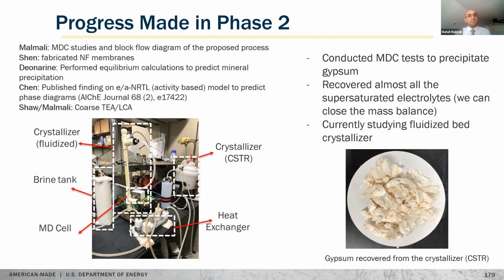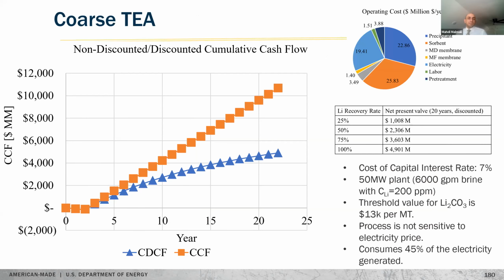So with Deonarine, we did some very basic thermodynamic studies on equilibrium calculations to predict the mineral precipitation. And also Chen published a very accurate activity-based model called e/a-NRTL to predict the phase diagrams for lithium chloride. And in the next phase, we want to do experiments with lithium carbonate and lithium hydroxide in order to get this model also working for them, and essentially use the model from the beginning to the end to predict the performance. And with Shaw, we did some course TEA and LCA, which I will tell you a little bit about. Next, please.